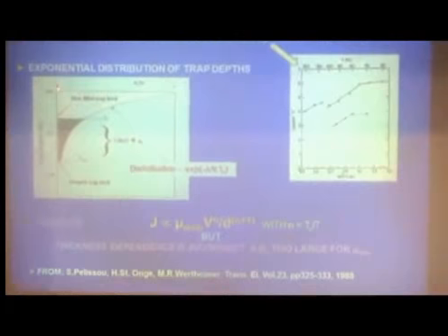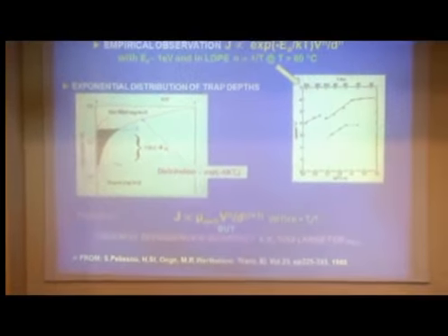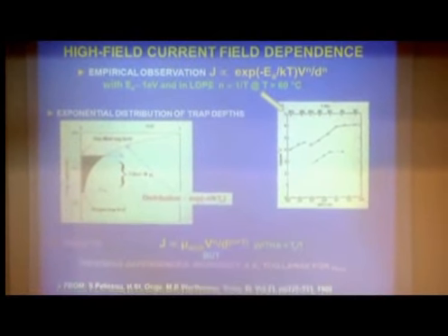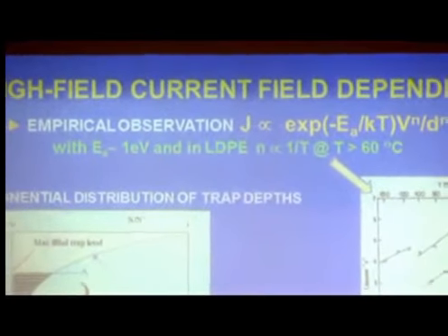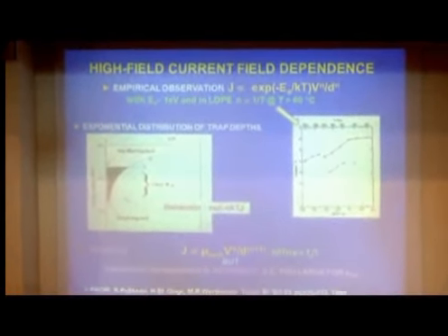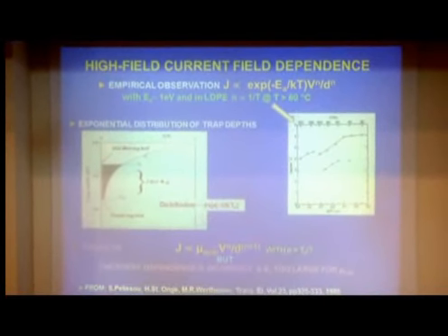Second thing is the mobility of the free carriers promoted up to some level here. You may expect that that has some thermal activation involved because there are no extended states in the polymers. But you wouldn't expect activation energies of this level, perhaps 0.3, 0.5. And as I said, the previous data that I showed you has values between 1.6 eV and 1.9 eV. Although it's attractive to think that this theory represents the data, in detail it doesn't.